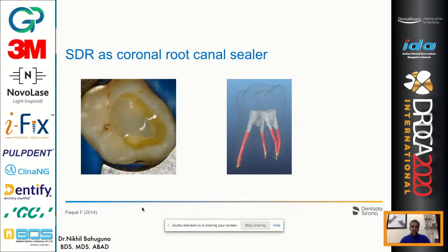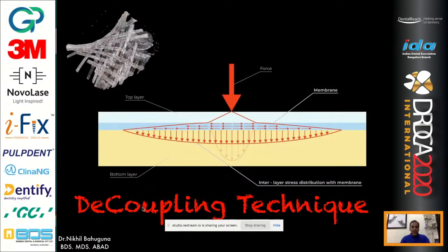When my dear friend Dr. Deepak Mehta and I, who were batchmates in post-graduation, got the concept of breaking the junction between the two layers, because the moment we do that, the bottom layer doesn't pull up, it stays. So the chances of micro cracks, micro leakage, and the potential pulpal stress are totally negated. We started with bifluoride varnishes, we used a lot of glass fibers, polyethylene fibers, and finally now we're using the Dentapreg fibers for all the obvious good points it has. When we place that on top of that primary 0.5 to 1 mm layer and cure it, because it's pre-adhesed, it attaches to the composite and the pull of the curing gets down.